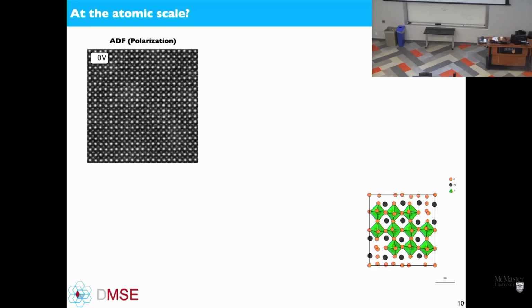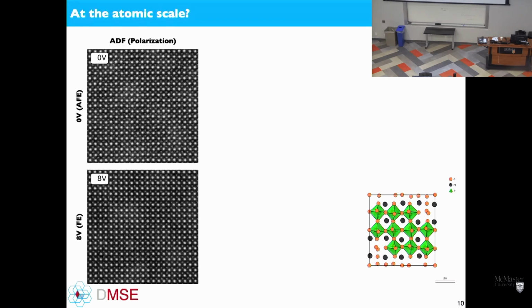And so here's an example from annular dark field STEM. Again, we're only seeing the cations here at 0 volts. As I start to apply a bias, you can see the shuffling of those atoms where it switches. That's the transition from an antiferroelectric to a ferroelectric at higher voltages. So again, just kind of showing here, as the switch is up to 8 volts, it becomes what looks like essentially cubic or tetragonal, it's actually tetragonal at 8 volts, or ferroelectric.